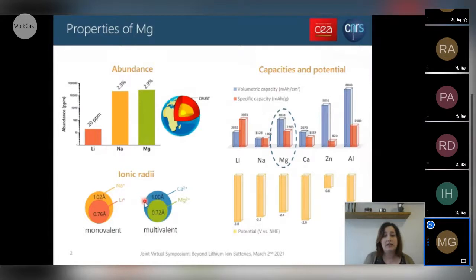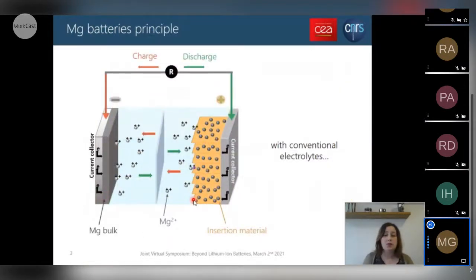And finally, magnesium 2+ presents a smaller ionic radius than lithium, while in fact it carries 2 charges, which thus leads to low diffusion of magnesium ions in solids. The working principle of a magnesium battery is similar to the one we've seen for lithium-ion or sodium-ion batteries, with an anode, cathode, and electrolyte. But the main challenge in magnesium batteries is that with conventional electrolytes, there's an incompatibility with the magnesium negative electrode. In fact, when conventional electrolytes, such as carbonates, are in contact with magnesium metal electrode, there's the formation of a completely blocking passivation layer that inhibits the exchange of magnesium ions to strip or plate the magnesium metal electrode.